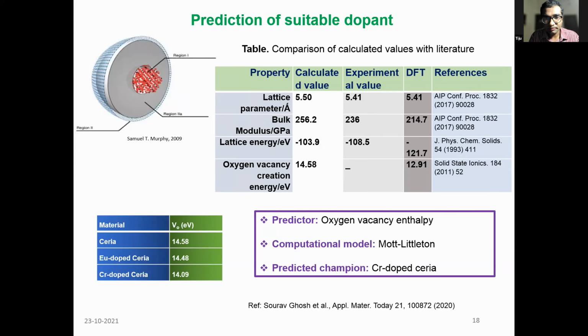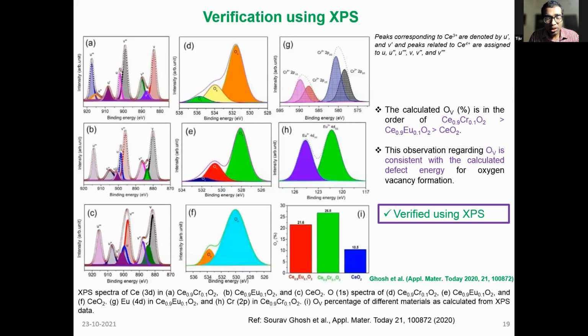So next, please. So the prediction here was, of course, that you will find that chromium, in this particular test case, that is, chromium and europium, both of them would certainly introduce oxygen deficiencies in ceria. But that is not it. Based on the delta H values, we found that chromium in particular would introduce more oxygen vacancies when compared to europium. And certainly both of those materials would have larger oxygen vacancy concentration when compared to standalone pristine ceria.